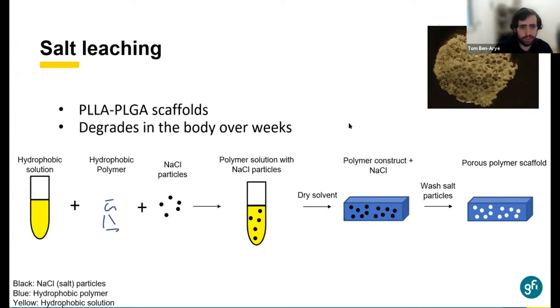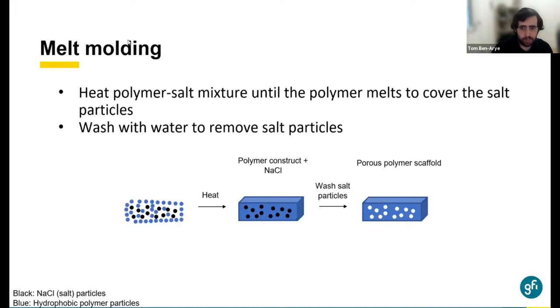That's one technique. Another technique is melt molding, very similar, but easier to understand. Basically, you take pieces of a polymer, you put them with salt particles, you heat them until the polymer melts, and then you get a construct of the polymer with salt particles, which you can then wash and generate a scaffold, a porous scaffold as we saw before.